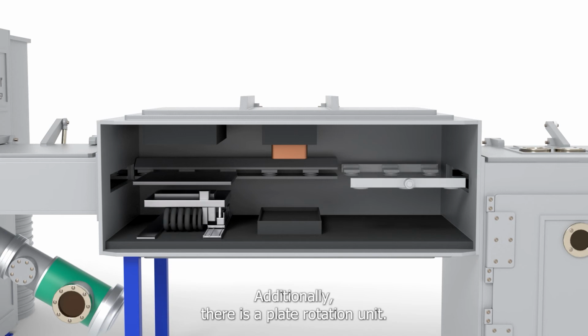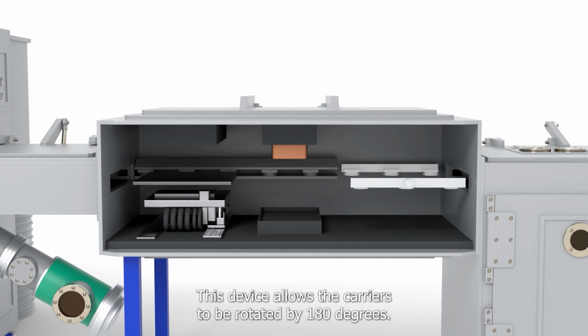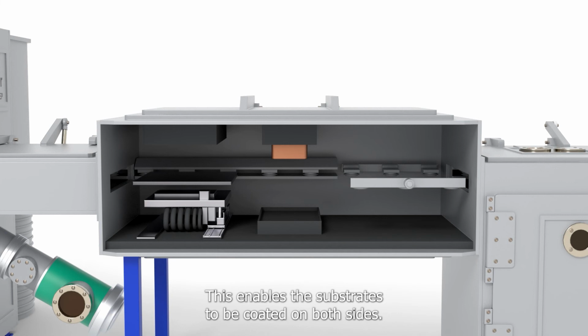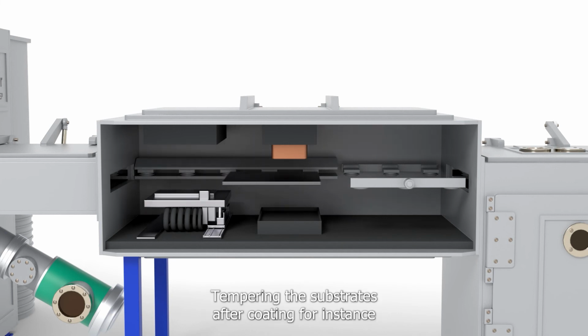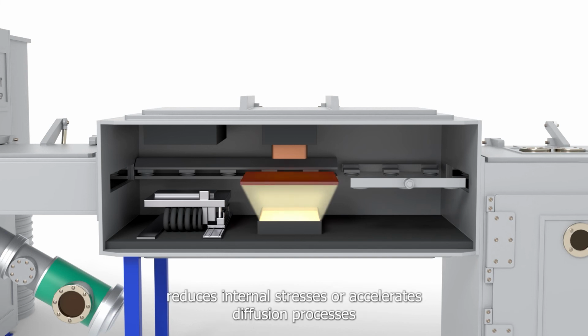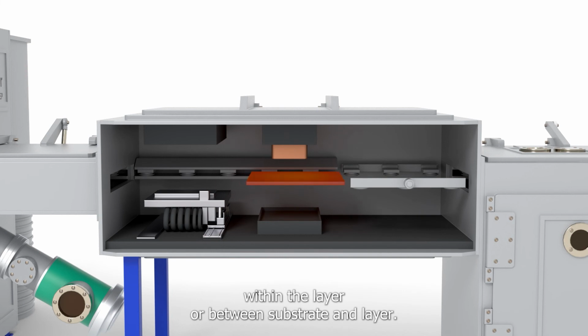Additionally, there is a plate rotation unit. This device allows the carriers to be rotated by 180 degrees. This enables the substrates to be coated on both sides. Tempering the substrates after coating, for instance, reduces internal stresses or accelerates diffusion processes within the layer or between substrate and layer.